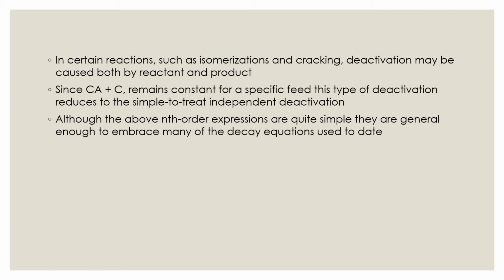In certain reactions, such as isomerization and cracking, deactivation may be caused both by reactant and product. Since C_A plus C_P remains constant for a specific feed, this type of deactivation reduces to the simple-to-treat independent deactivation. Although the above nth order expressions are quite simple, they are general enough to embrace many of the decay equations used today.